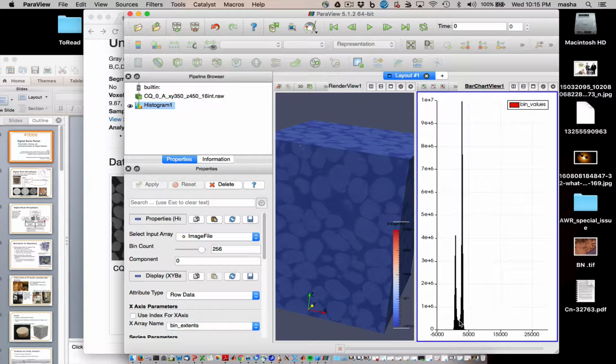So essentially, if I strike a surface somewhere around here, I can look at the histogram and explore it a little. I think I have this dip at 1600. So around 1600, I'm not going for very high precision here, but around 1600, I can actually see that I should have a good difference between what are pores and grains in this image.